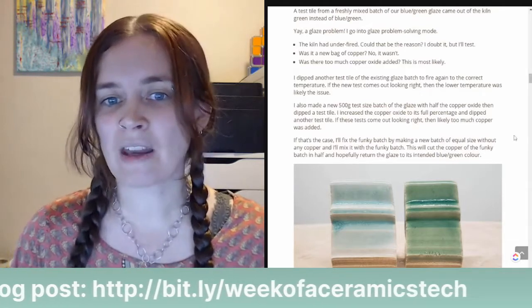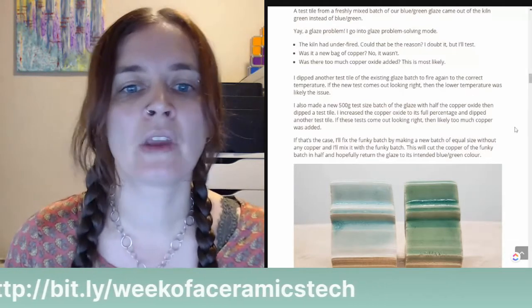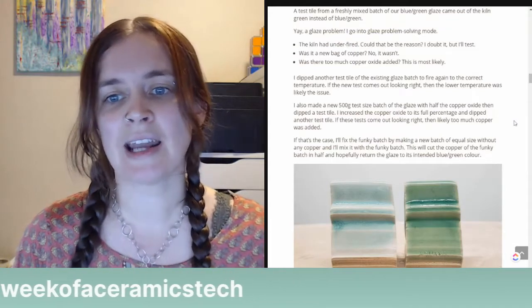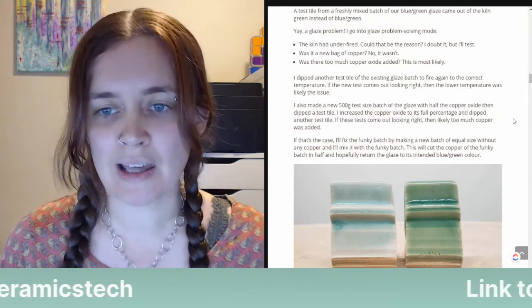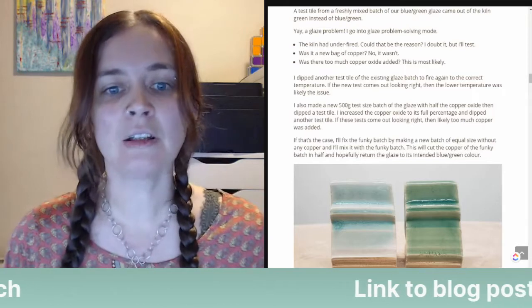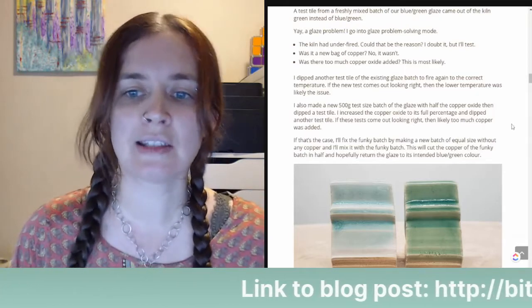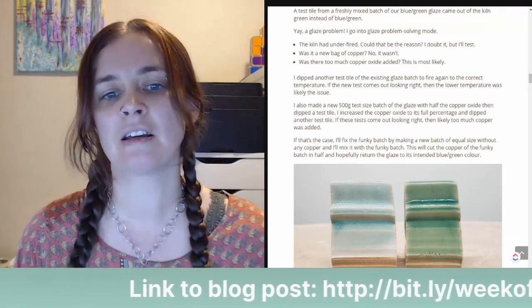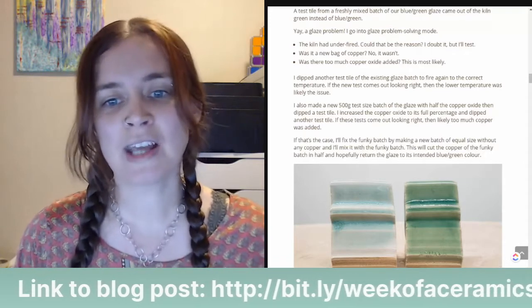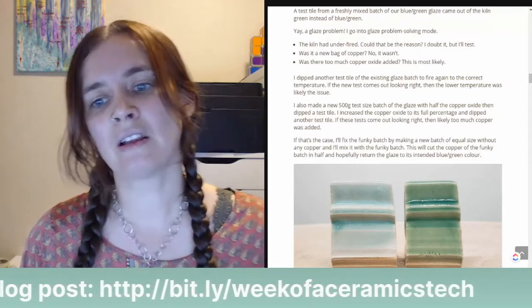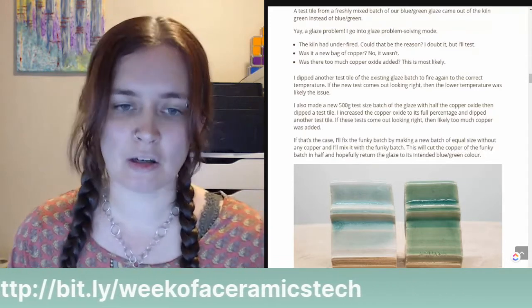Was it a new bag of copper? No, it wasn't. Was there too much copper oxide added? This is the most likely scenario. So I dipped another test tile of the existing glaze batch to fire it again to the correct temperature. If the new test comes out looking right, then the lower temperature was likely the issue.